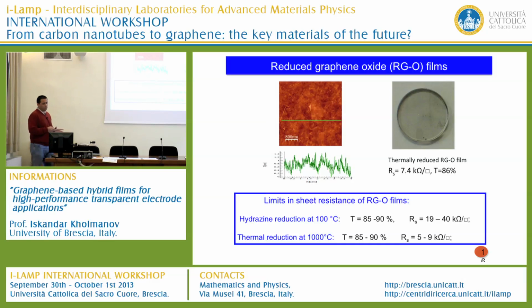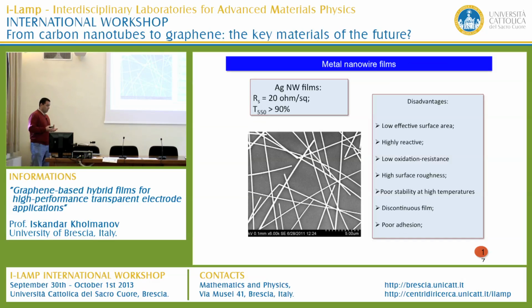So we tried different methods of reduction, and there is today no method that can produce reduced graphene oxide with a sheet resistance lower than 1 kilo ohm and with an optical transmittance higher than 90%. So the reduced graphene oxide film itself cannot be used as a transparent conductive film. However, it is very efficient in fabricating hybrid films.